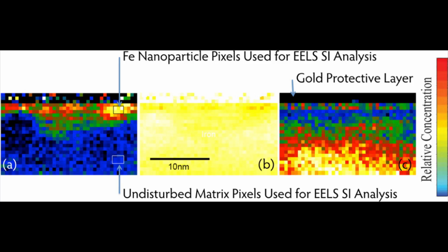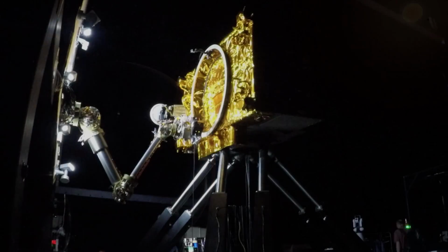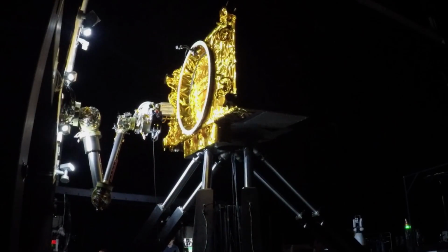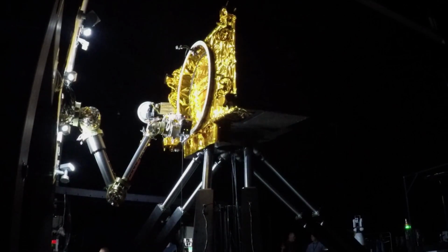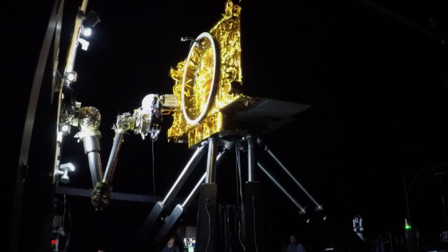The orthopyroxene exposed to hydrogen looks similar to the sample exposed to helium. However, the iron appears to have clumps of nanophase iron instead of a more or less clear band. Known as Ostwald ripening, these clumps grow due to thermodynamic processes that favor larger nanophase particles. Space weathering is constantly happening to exposed bodies in the solar system. To learn more, scientists are developing sophisticated techniques to accurately simulate the actual phenomenon here on Earth so they can scrutinize the process.